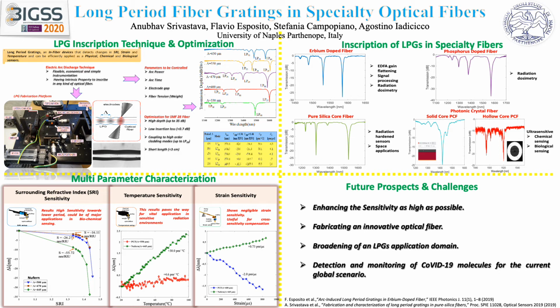So for the characterization aspect, multi-parameter characterization, that is surrounding refractive index, temperature, and strain sensitivity. We tried with Nufern and photonic crystal fiber and put them under these characterizations. We achieved for Nufern that for SRI, as you lower the grating period, you get higher sensitivity, which we achieved around 55.72 nanometer per RIU. So it can be used in biochemical sensing.